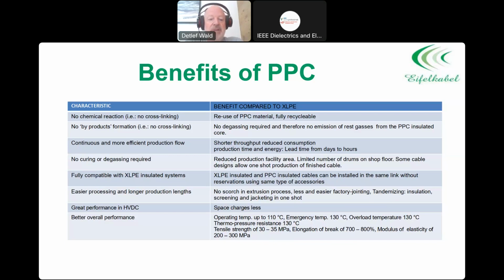The other thing is, again, no curing, no degassing. No curing means you don't have to heat up the cable to reach 180, 200 degrees. You can immediately cool it down. That means the space that you need for the production area is significantly smaller.